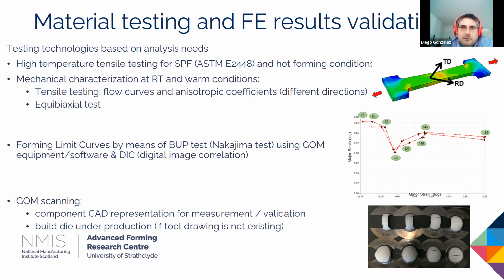In terms of failure, obviously we need to know the limits of the formability of the material. We have the BUP testing based on Nakajima test samples, and coupled with this BUP test, we have GOM equipment and a digital image correlation approach. And when we need to validate the material, the simulation and the model, we can proceed with GOM scanning of the components and compare the thickness of the formed component against the results of the FE simulation, or we can compare the shape of the formed component with the FE results.